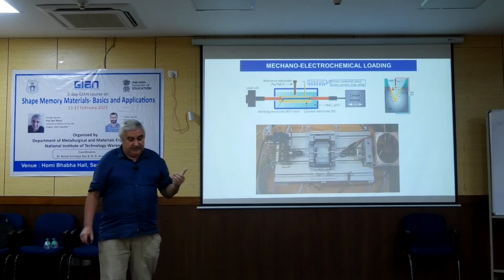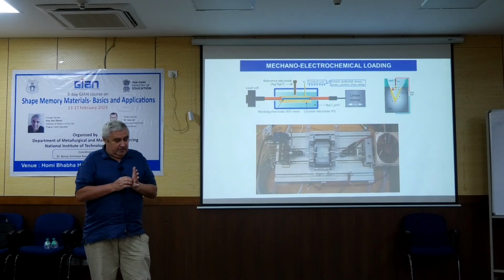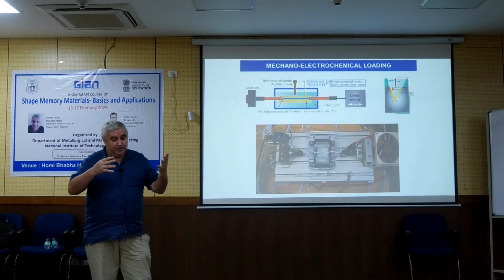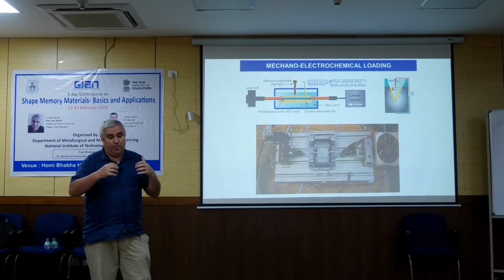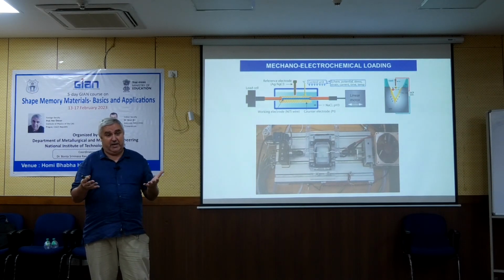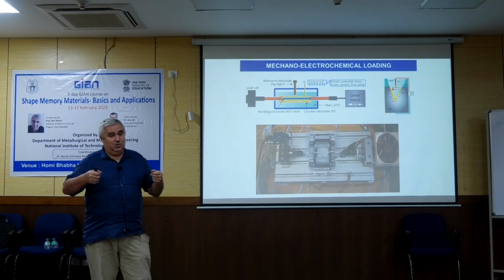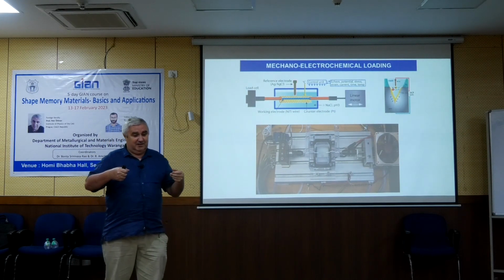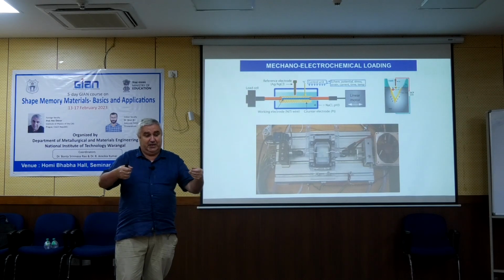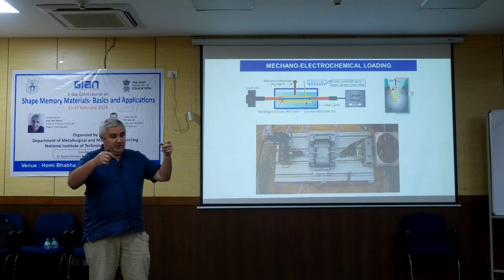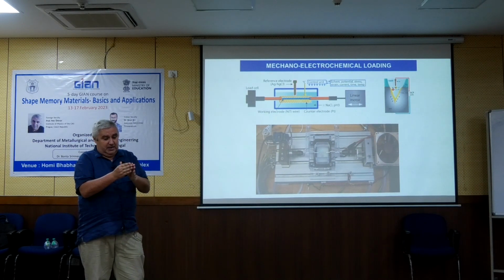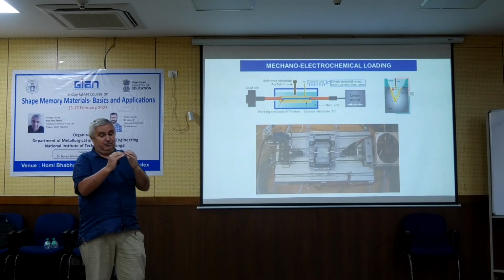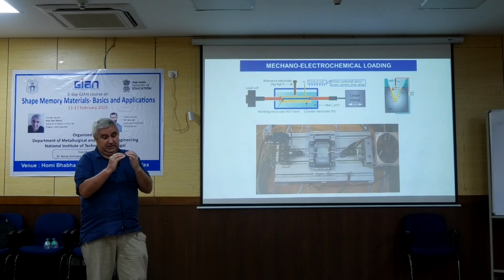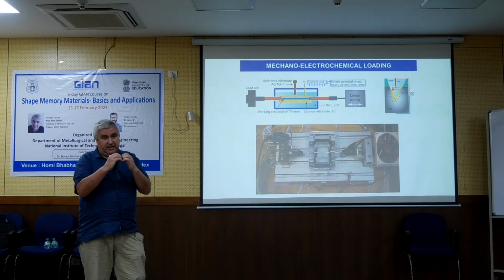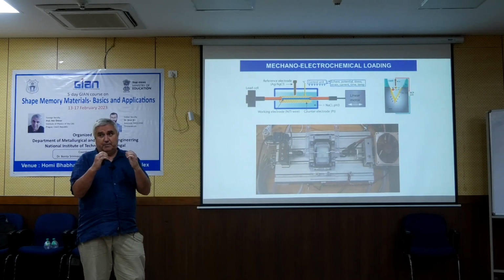So then when we learned that healing will solve the problem if the cracks are not periodically opening, we came to the conclusion we should make some experiment where during the experiment the cracks will open and close, and we will try to observe whether there is any reaction with this electrochemical experiment. Because if you measure the electrochemical potential with the electrode, this is sensitive to the layer which is on the surface, basically only to the oxide. It doesn't see the metal.